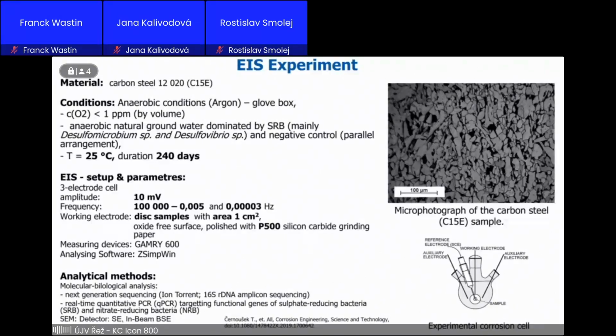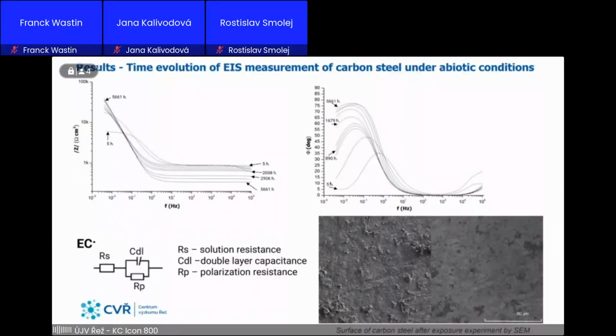Here you can see the experimental setup for electrochemical impedance spectroscopy. The amplitude was 10 millivolts. The frequency range was from 100,000 hertz to 5 millihertz. In the case of the biotic environment, where there were microorganisms, we had to reduce the frequency to get information about the corrosion rate. As analytical methods, we used next-generation sequencing and real-time quantitative PCR.